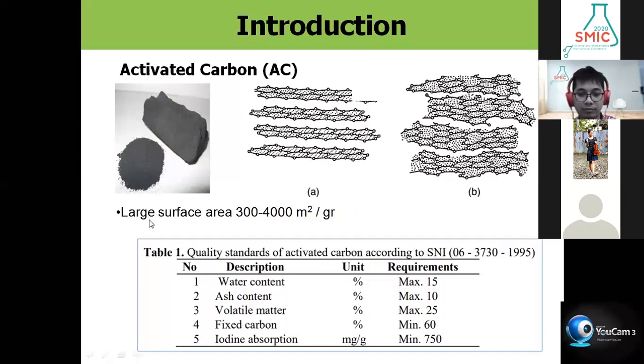The interesting thing about activated carbon is that it has a very large surface area, 300 up to 4,000 square meters per gram. By seeing the structure, we can expect that this material can be very potential as an adsorbent. For using activated carbon for many purposes, especially water filtration, Indonesian national standards have set requirements. For example, water content must be less than 15%, ash content less than 10%, volatile matter less than 25%, fixed carbon at least 60%, and iodine absorption at least 750 milligram per gram.